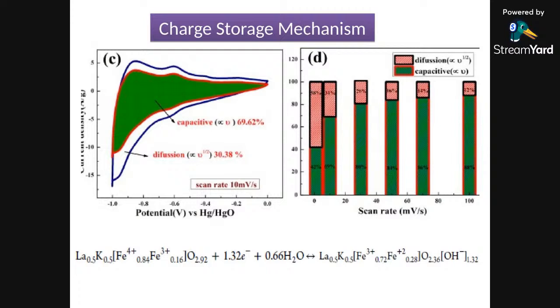So when we did our charge-discharge, the energy storage was very high. The diffusive type of storage itself is only 30%, but the capacitive is close to 70%. So what we found in the mechanism is that in this perovskite material an interconversion is happening very heavily, rather than intercalation or an excess. Oxygen actually gets reduced to hydroxide ion, and this is the way iron 4 and iron 3 get reduced to iron 2, and we get such a high energy storage.